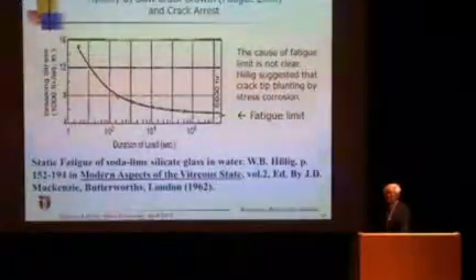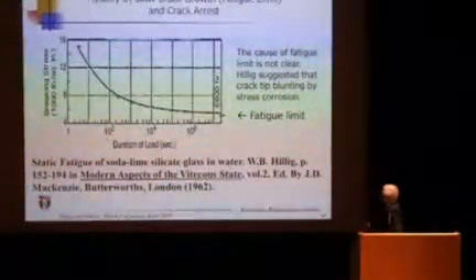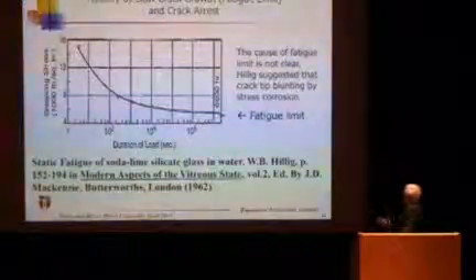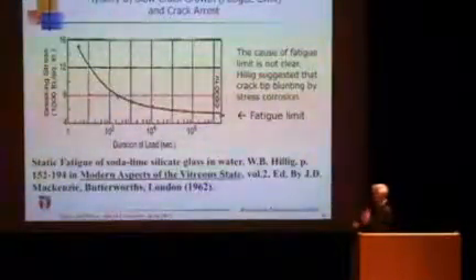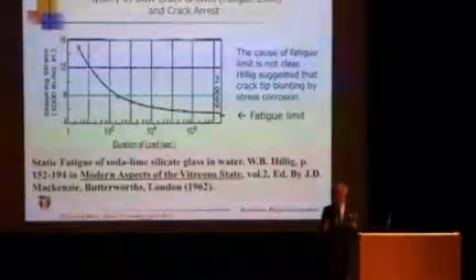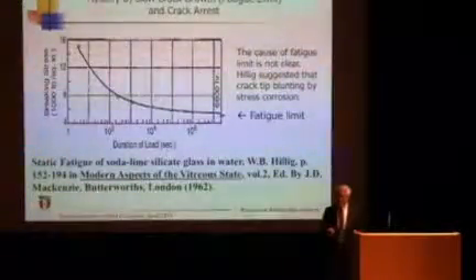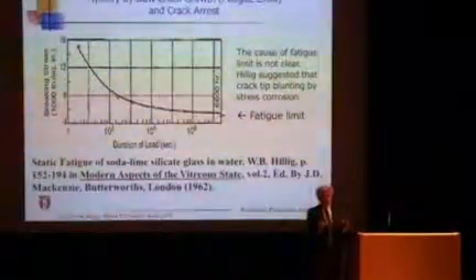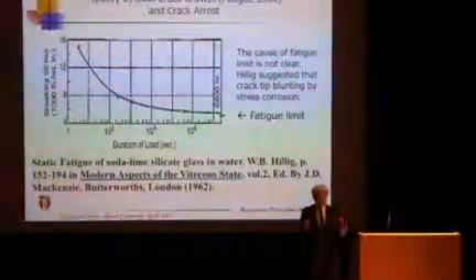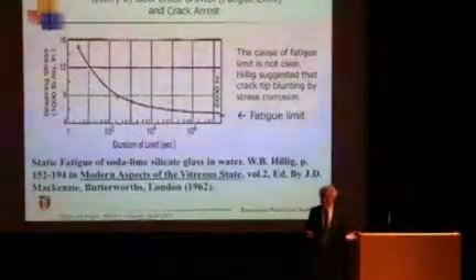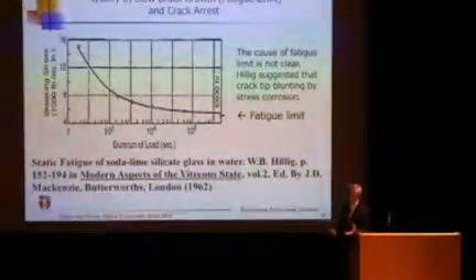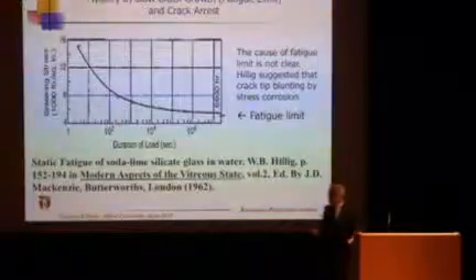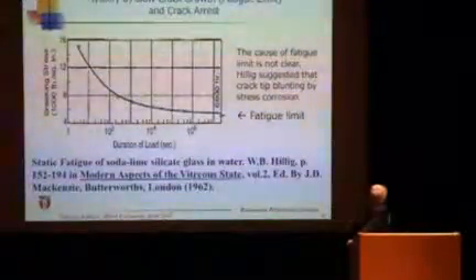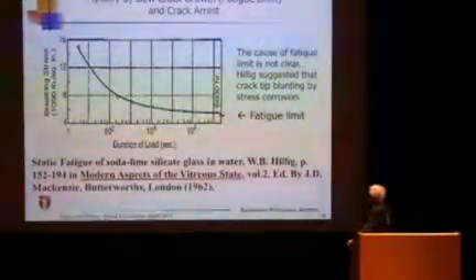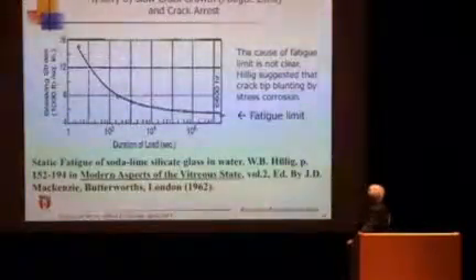The other mystery in this field is fatigue. As I mentioned, if you apply a constant load, glass would not break instantaneously, but after a certain time, glass will break. That's just like a human being, glass getting tired. And that normally is related to the moisture effect, water effect. And this shows the logarithmic time scale. This requires great patience to do this experiment.